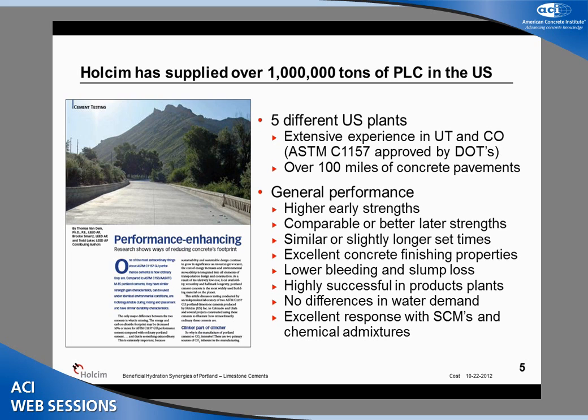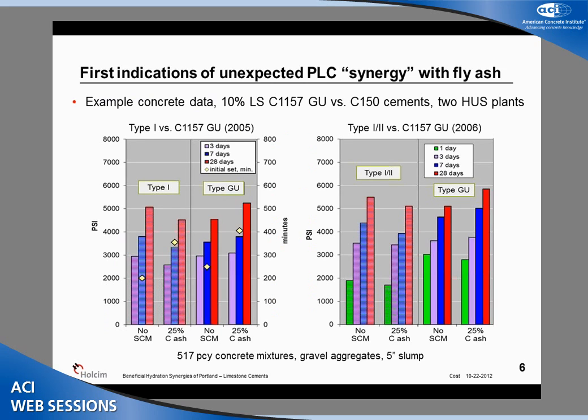Holcim has supplied over 1 million tons of Portland limestone cements in the last few years under C1157. Many of the other cement companies have similar reports of experiences. We've had quite a bit of success with these products and found their attributes to be much as the literature review suggests. Much of the experience has been in the western part of the U.S. where the ASTM C1157 specification has been recognized by some states, and we now have over 100 miles of concrete pavements constructed in the states of Colorado and Utah using this material.